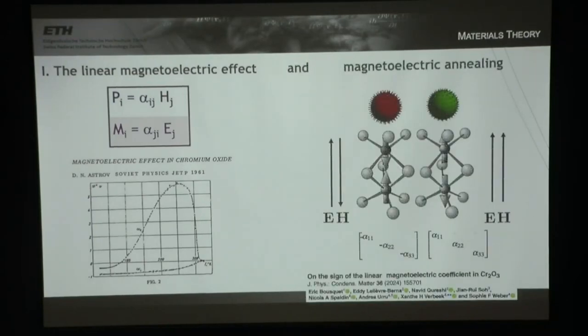The other nice thing is it's the same physics as the linear magnetoelectric effect. One can use this to select for a particular antiferromagnetic domain. So if I apply my electric and magnetic fields parallel to each other, I pick out one sign of the hedgehogs. And if I apply them anti-parallel, I pick out the opposite sign of the hedgehogs, because the two domains have the opposite magnetoelectric response. And so this has been done. It's very difficult to get the signs right in this.